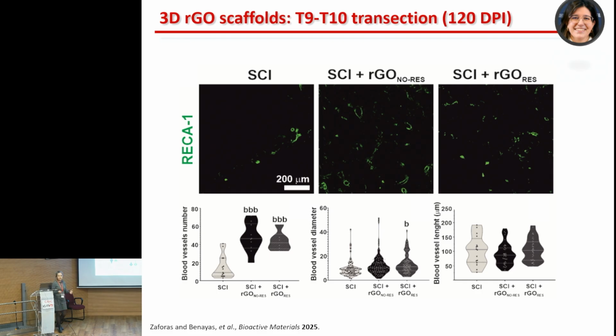But not only that, we also did an extensive histology of these animals. And again, we demonstrated, this is also after 4 months, as you can see here, same time point as the previous results that I showed you, we also get blood vessels. This is just the injury animal, and these are the 2 groups of animals that have our scaffolds, those in which we found the neurons that were responding, and those in which we couldn't detect those neurons responding. And in both of them, the response was very similar and much better than in the case of the injury. So a significantly higher number of blood vessels, and in the case of this particular group, even the diameter. For the rest of the parameters, they were similar to the injury.